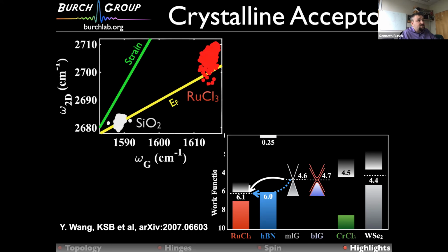I don't have time to explain how we did this, but basically if you use Raman spectroscopy, there are 2 key modes that are well known in graphene, the G mode and the 2D peak, and luckily they have different dependencies on doping and strain, such that if you measure both of them in your material, you can directly determine whether they're shifted from the ideal case by strain or doping or both.